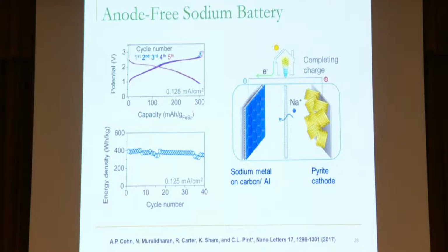So relative to the materials of pyrite, sodium, and the nucleation layer, the carbons that we use, which are super thin on the surface, we were able to get energy densities of about 400 watt-hours per kilogram. Well, that's pretty good, right? So, okay, what does that mean?